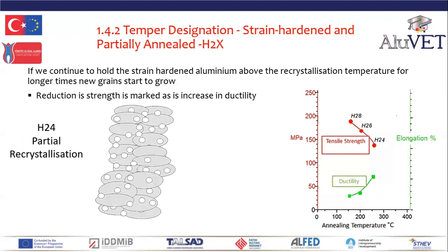As we continue to heat for longer times above the recrystallization temperature, new grains continue to grow. Accompanying the partial recrystallization, we experience an increase in ductility and a decrease in strength. This is the H24 strain hardened, partially annealed, half hard equivalent condition. This means by controlling the amount of recrystallization, we can manipulate the amount of new grain growth and so set the decrease in strength and the increase in ductility.